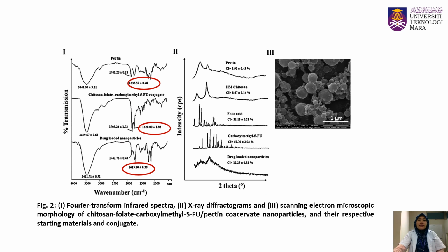The nanoparticle produced by coacervation of chitosan folate 5FU and pectin was confirmed by FTIR analysis, where there is a reduction in wave number at the 1615 peak, which is attributed to CONH interaction. The formed nanoparticles are semi-crystalline in structure, unlike CMFU, which is highly crystalline. Generally, the nanoparticles are spherical in shape.